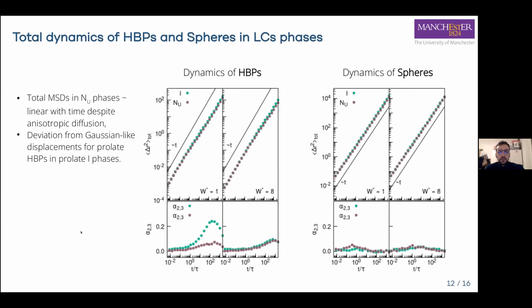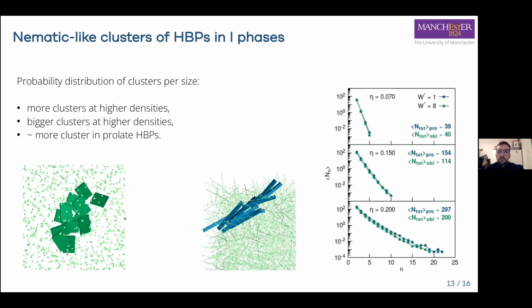For the total dynamics of the particles, we also computed the non-Gaussian parameter to see if we can observe deviation from Gaussianity. And interestingly, we observed a strong, more predominant deviation from Gaussianity at intermediate and long time scales for prolate particles in isotropic phases. And we try to give an explanation of this occurrence of deviation from Gaussianity in less dense systems, so in isotropic rather than uniaxial nematic phases. And for this reason, we tried to find the nematic-like clusters in isotropic phases that maybe can affect the diffusion of prolate and oblate cuboids.